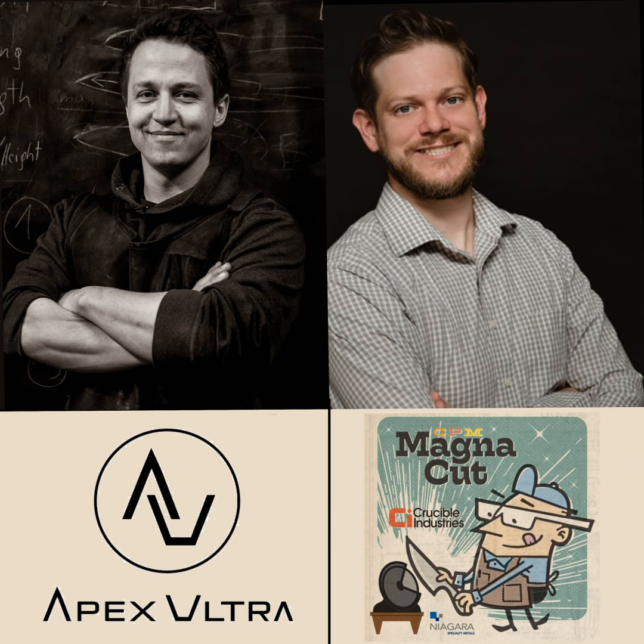That's my short answer. Is that understandable? So you're eliminating more variations throughout a batch of steel as it gets rolled and pressed and formed to shape. Exactly. So it's the same everywhere. If you see steel that shows beautiful alloy banding or carbide banding, that's very nice to look at in a knife, but it's not the greatest sign for the knife production itself or the processing, because it basically means it's not uniform. The steel has segregated again after cooling down. So is that making weak points in the steel when you see something like that?